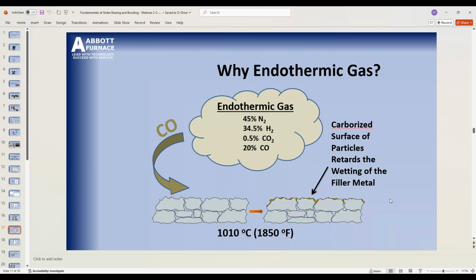Also, we can play a game with the atmosphere. We cleaned up the surfaces, right? Cleaned the oxides up, everything. We made sure it was all clean. But if you talk to a lot of old timers, they'll tell you, you have to have endothermic gas to sinter braze. Well, not really. The reason it works is if I have material coming in here at about 1,010 degrees Celsius, endothermic gas contains carbon monoxide, CO, about 20%. CO, when exposed to iron at that temperature, the carbon will actually deposit onto the surface and it'll carburize the surface slightly. So by putting a little bit of endo in there, because you've got a pretty stable gas and you're trying to carburize, it only puts a really, really thin film of carbon on the surface.